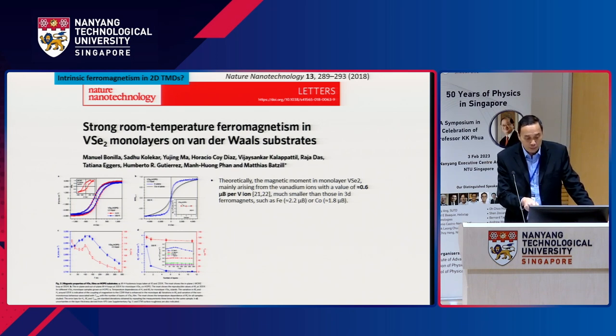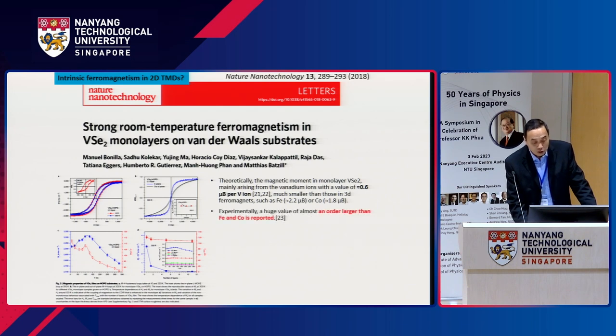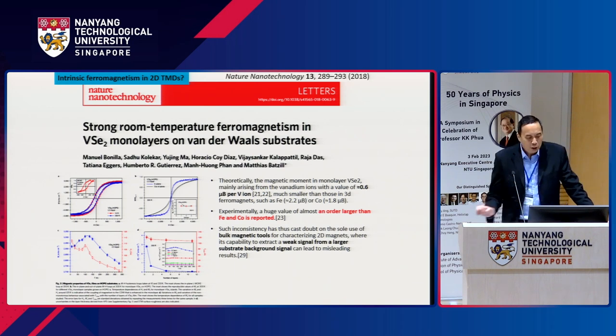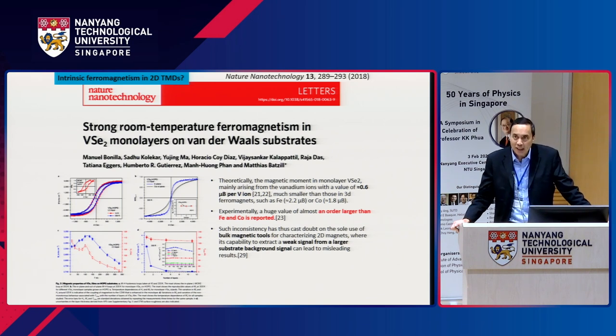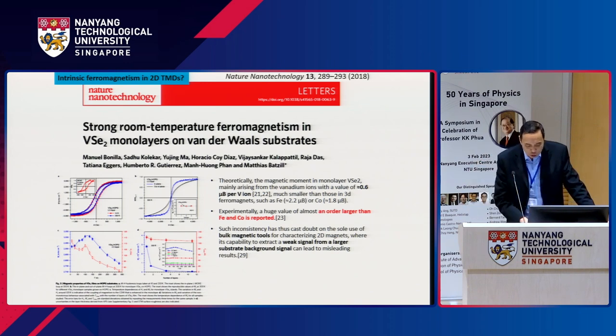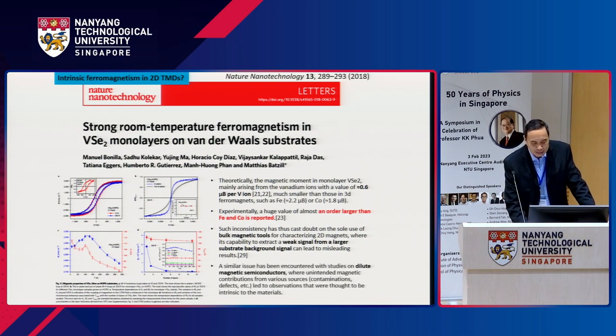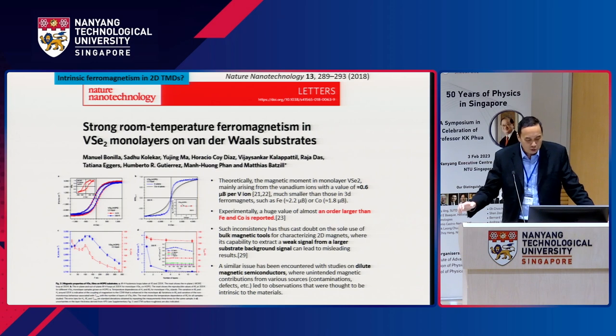Theoretically, the value should be 0.6 μB per vanadium ion, but the value they got was an order of magnitude larger. And we were quite suspicious about this, because the method they used for measuring the magnetism was SQUID, which is a bulk method. If you're trying to measure a magnetic property from a very thin layer out of a thick layer, chances are that you will pick up signals from the bulk or contaminations around.